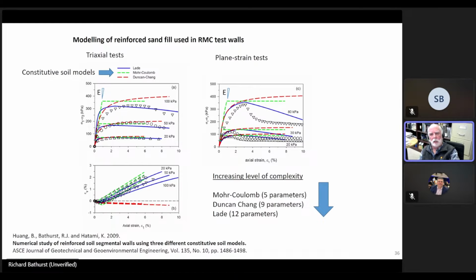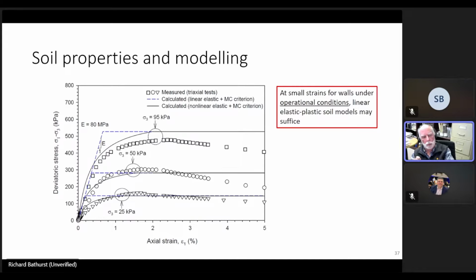But it's interesting that if you're interested in walls that are under operational conditions and the strains in the soil and the reinforcement are quite low, you can often get away with a simple linear elastic plastic model, as long as you're able to get a reasonable estimate of a single value of the elastic modulus. And that's because we're operating at very low strain levels. And maximum strains in geosynthetic reinforcement materials under operational conditions are almost always less than 1%. So this is evidence in support of how we can simplify our models by simply using linear elastic Coulomb type models.